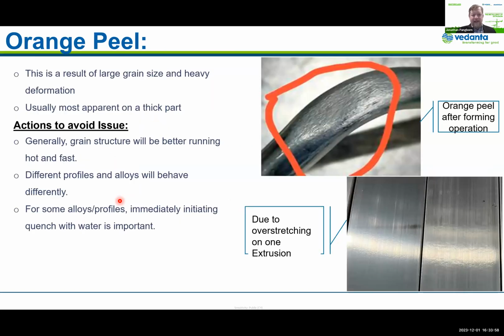Okay, moving on to orange peel. This is another common issue, particularly on heavier shapes, and is basically related to the grain size of the part. When you're deforming, the individual grains in the material, because of crystallographic orientation, have ways that they want to be arranged, and so they rearrange themselves a little bit. It's enough on large grain material that you can actually see a visible representation of that.